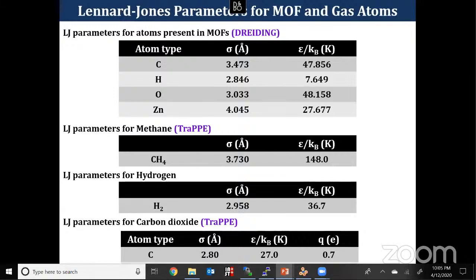The one disadvantage here is that if you use more atoms in a computational study, your calculation running time will increase. So in order to reduce it, we should not compromise on accuracy. For that, we already have force field parameters for the gas molecules that I used. Here we use the united atom approach, which means the methane molecule is considered as a single sphere model. But carbon dioxide is treated as a three-site model. It has carbon as well as two oxygens in the molecule file, and they have their own charges as well. But in the united atom approach, we normally won't go for charges.